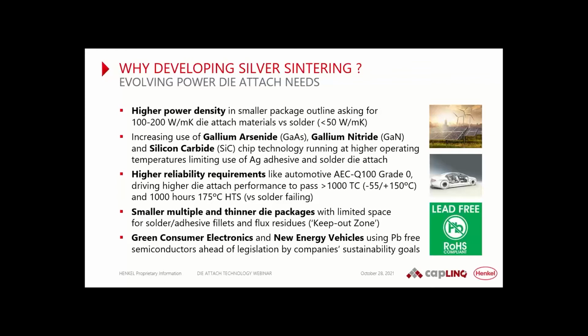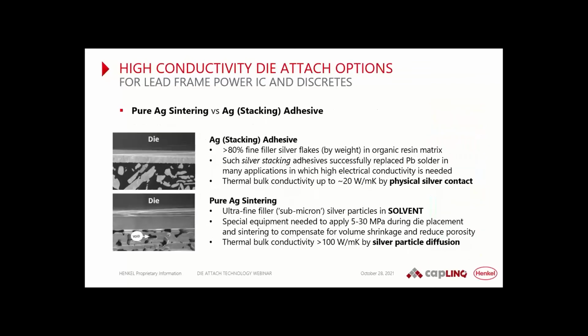Customers and end users, especially in consumer electronics, but also now in new energy vehicles, like to offer true green solutions, so not having still some lead in the power semiconductors. So basically, what is sintering versus the stacking adhesive? The stacking adhesives Chris already covered, like the QMI529HT, right? Now, the big difference is you have the physical contact in the case of the stacking. You can see that here on the picture on the left. So it's physical contact, while for sintering you really get the diffusion leading to a really metallic joint. So I think that's the key difference.